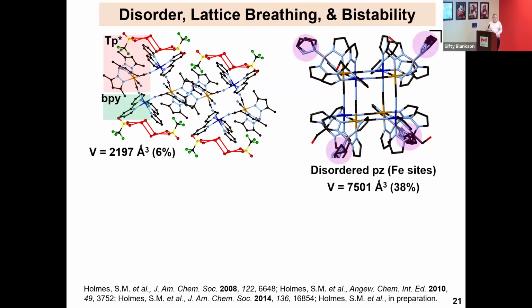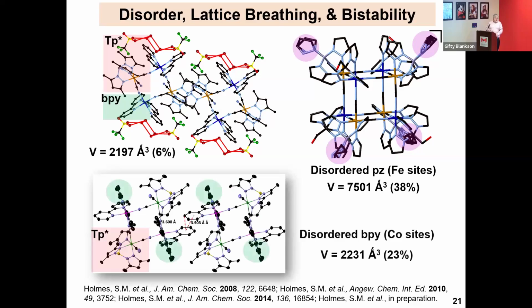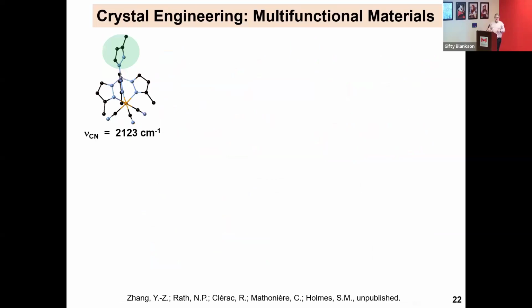small in this case, where we didn't see any behavior changes. Likewise, in the Angewandte Chemie paper, 2010 paper, we see lots of action around the bipyridines on the cobalt, and suffice it to say, they're either doing jazz hands or they're wiggling like that. That wiggling is giving you the volume space necessary to allow for the expansion and contraction. And lo and behold, solvent volume around that is large, further minimizing intercluster interactions that shut down your electron transfer.